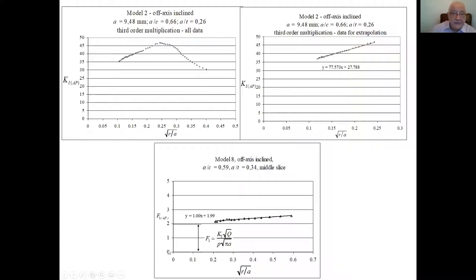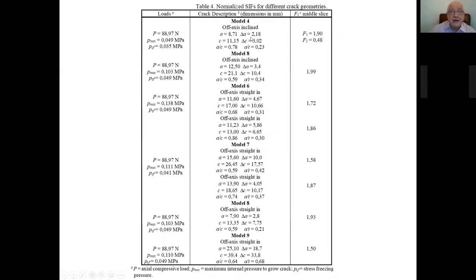So this F1 value, as it is notated here, which has been established, is the ratio, kind of a normalized stress intensity factor using this relation we were talking about. Here are the middle slices, so the slices at the maximum depth of the propagated crack, different models. Looking now at different measurements and different models, what we can see is essentially, if you look at least at this, you have different positions of the crack, off axis straight in or off axis inclined. And at the end, we were looking for the F1 value, so this means mode 1 in the middle slice. We had also slices at some other positions close to the surface at 20 degrees.